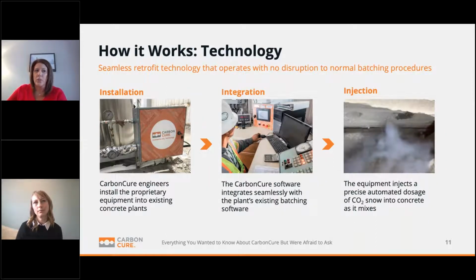So how the technology works. CarbonCure's technology delivers a precise dose of CO2 into the concrete mix, just like any other admixture. Our system is integrated with the batching software at each individual plant, which means it's communicating with that software automatically to deliver the right dose of CO2 for each concrete load that's being batched. The CO2 itself is dosed by weight of cement. So the exact amount of CO2 will vary with the different mix designs, depending on how much cement you have in those mixes. But on average, what we're injecting is about 1 pound of CO2 per yard.